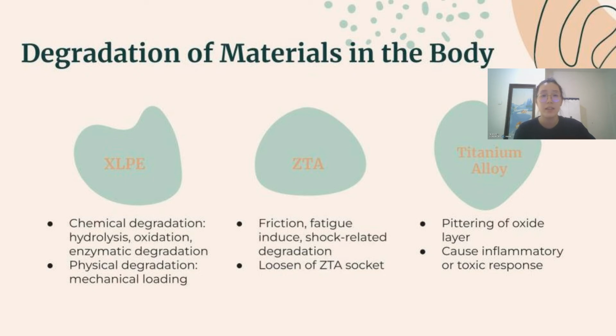The degradation of the ZTA component of the femoral head accelerates the degradation of titanium alloy, which makes the femoral stem. The titanium alloy, which is covered with a thick titanium oxide layer, is protected to prevent corrosion. However, as time goes on, the oxide layer may be mechanically removed or loosened due to metallic debris, which is caused by extreme positions achieved during gait routine. The wear particles caused by degradation may lead to inflammatory or toxic response, even though the bulk materials are biocompatible.